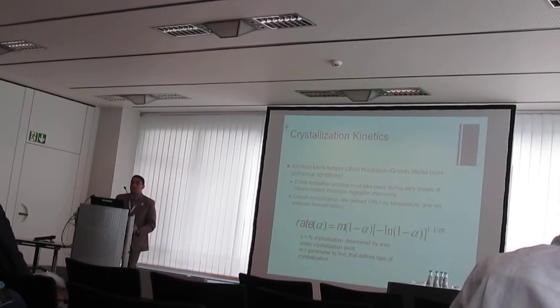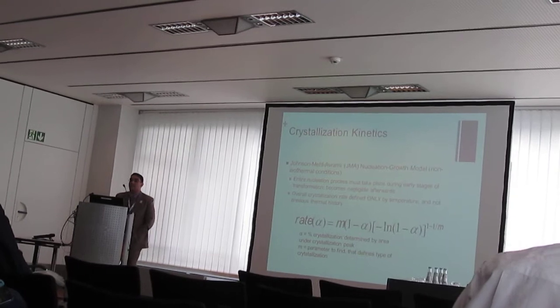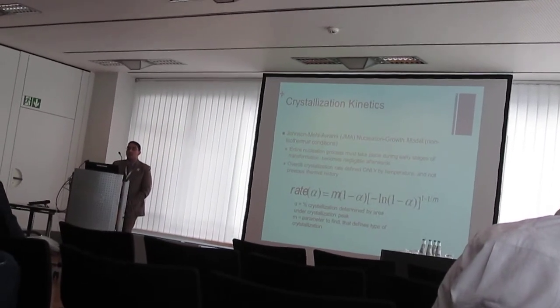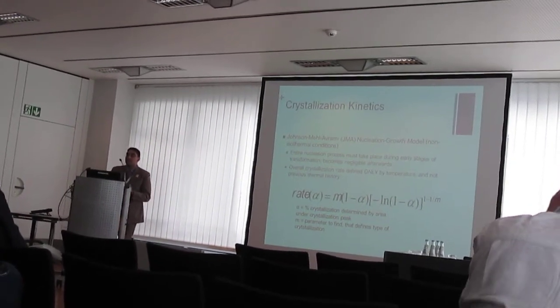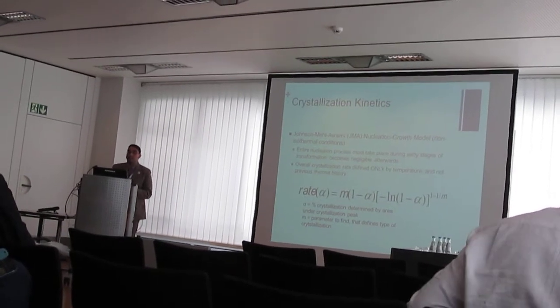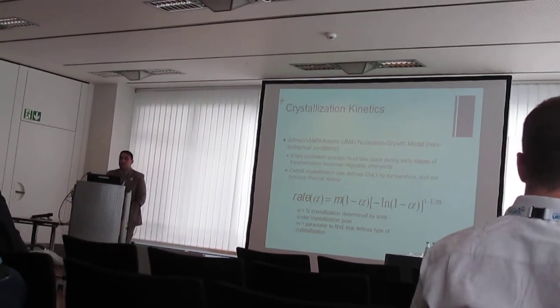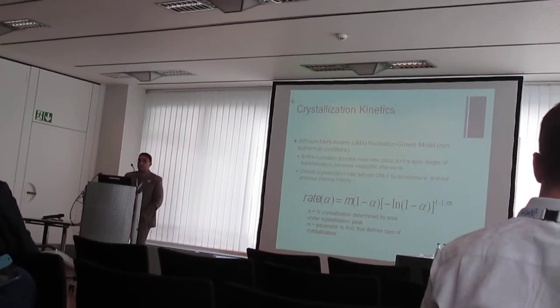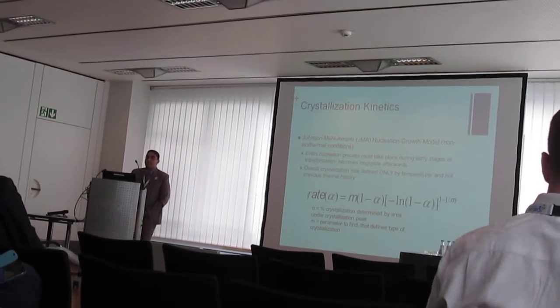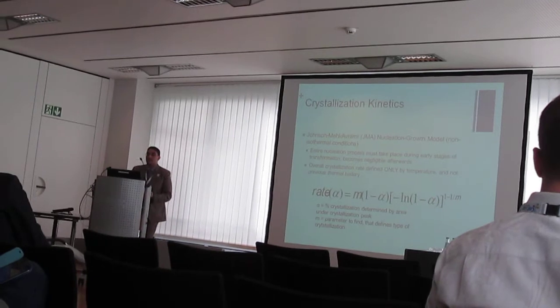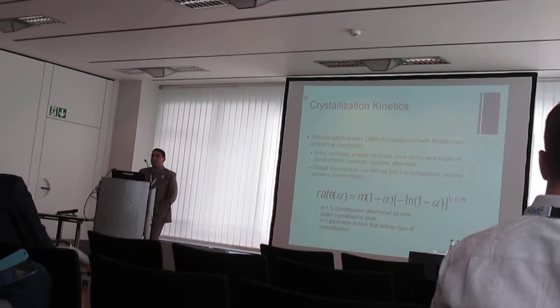Now there are 2 conditions that have to be satisfied for this model to be true. The first is that the entire nucleation process must take place during the early stages of the transformation and has to become negligible afterwards. Secondly, the overall crystallization rate is only defined by temperature and not by previous thermal history.